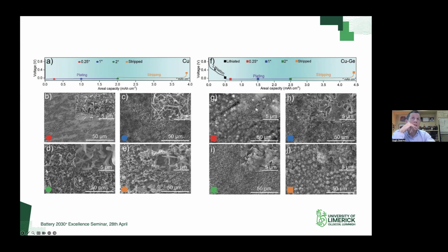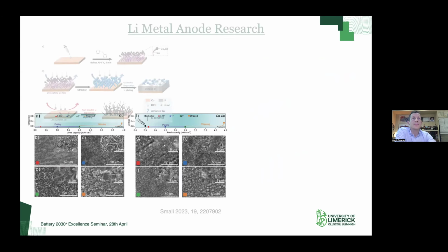So if we look at the characteristic lithiation profile of germanium, the germanium nanowires that you have there remain mostly lithiated, which actually means that it's a very stable morphology. The restructuring that I mentioned previously that happens during lithium-ion cycling would usually only happen if you fully alloy and dealloy that structure. In this case, this host is very, very resilient and will not change over time with cycling. And that's why we're able to get this long-term stability in the cells.